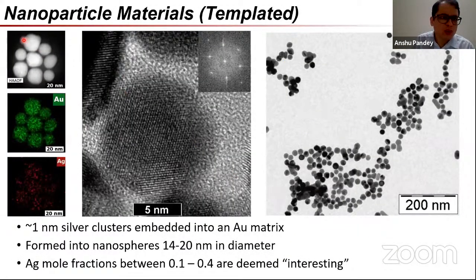So moving onward, if we look at nanoparticle materials which are made via the template route, on the basis of our earlier measurements, what we have here are 14 to 20 nanometer spheres, and we considered a range of stoichiometries, from 0.1 to 0.4 in this case. In this example, we have a 14 nanometer or thereabout sphere, but other particles would, of course, range in different sizes, all the way up to 18 nanometers.